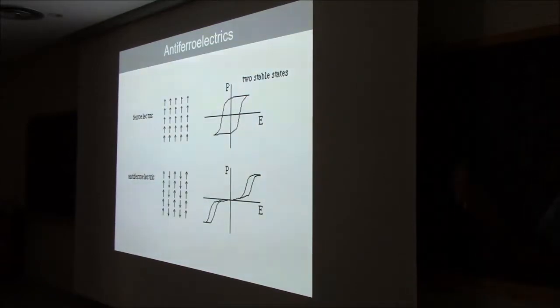But I will tell you this, the archetypal antiferroelectric, the one that we study, is lead zirconate, which is almost the same as lead titanate. So you have a lone pair in the A site, which is the lead 2+. It's just that the zirconium is a much bigger atom than the titanium, and so that gives you octahedral rotations that result in an antipolar configuration. But perhaps this lone pair polarization that is useful for ferroelectricity is also useful for anti-ferroelectricity.